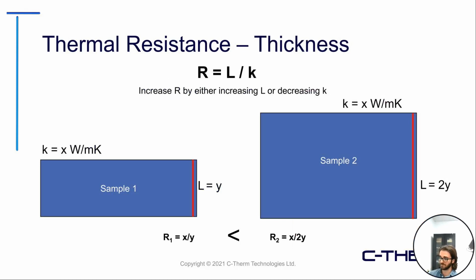So just a couple examples here, maybe a little thought experiment. Thermal resistance, if you're trying to modify it, can really be done in two ways. We notice that resistance is equal to the length or thickness of your material divided by conductivity. Therefore, increasing your R value, your insulative performance, can be done by either increasing the thickness of the sample or decreasing K. In this example, we're looking at samples 1 and 2. Both are presumed to have the exact same conductivity, so it's the same material, but one has twice the thickness of the other. If you were to plug this in, you would notice that solely based on the differences in thickness, sample number 2 has a much higher R value, because we're dividing the thickness by the conductivity, giving a larger number in the numerator and therefore a change in R value.